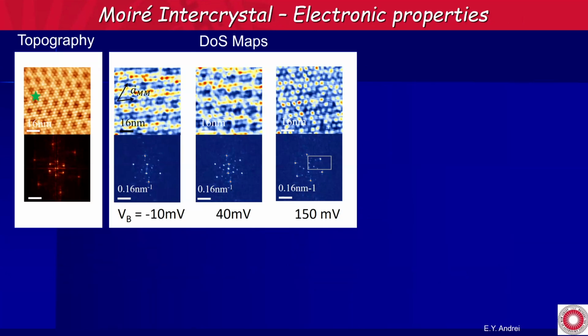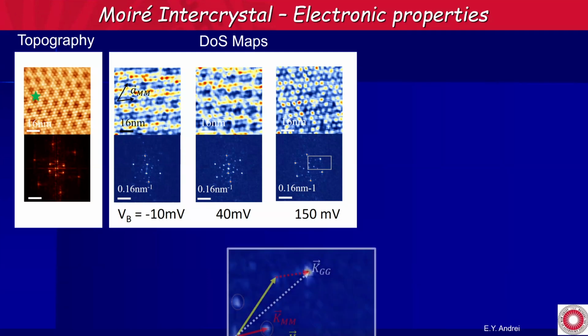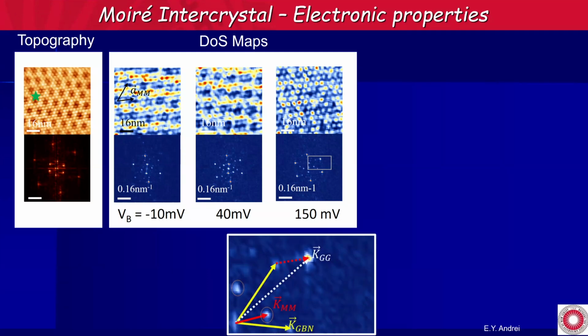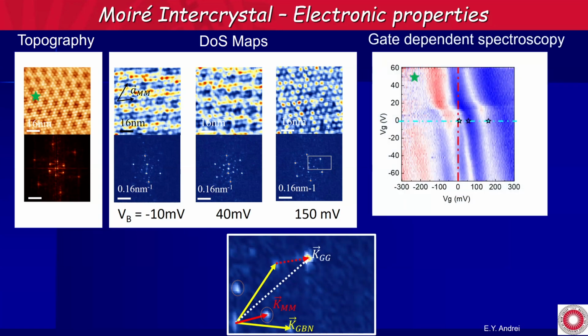Okay, so here we have the same thing, but now for an intercrystal. This is the topography, and I'm doing a density of states map as a function of energy, and now it's very different. You see stripes, you see squares. In the Fourier transform, you've lost the six-fold symmetry. You go from one symmetry to another. This is the zoom into this region of the Fourier transform. And if I do the gate-dependent spectroscopy now, it's very, very different. I do still have a flat band. I still open a gap when the Fermi energy is in, but it's very different from the standard TBG.